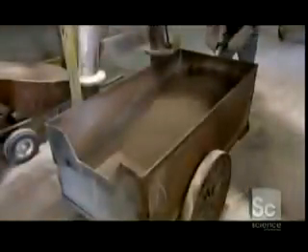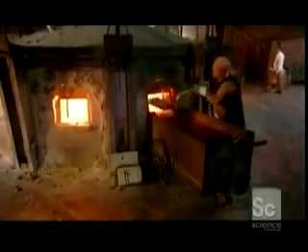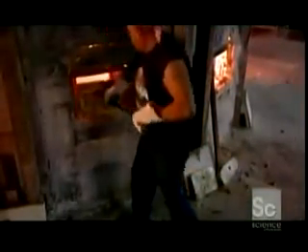The blended batch now goes via wagon to the beehive, a furnace that contains 12 ceramic pots. The furnace worker shovels the batch into a pot to melt at a searing 2600 degrees Fahrenheit. He pushes any spills back into the pot. Then, to control the temperature inside, closes up the pot's mouth. 24 hours later, workers scoop out the glowing molten glass.